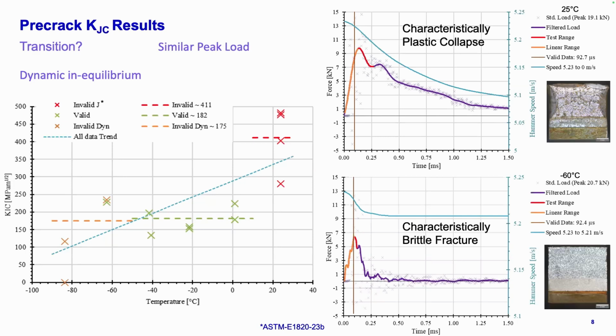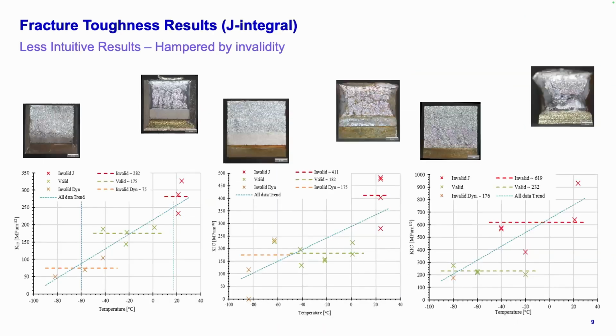Looking through all that data, I can look at the force and the force history, and look at the geometrical method for the toughness. This is where we come into these sorts of tests for the different setups. Green, good. These were ones that lay quite well with validity testing, that these were valid tests. They ticked all the boxes required. They weren't fully plastic collapsed before we could observe the critical value for fracture. Red, bad. Plastic collapsed before it went down. So it's a very ductile material, there's no useful data there.